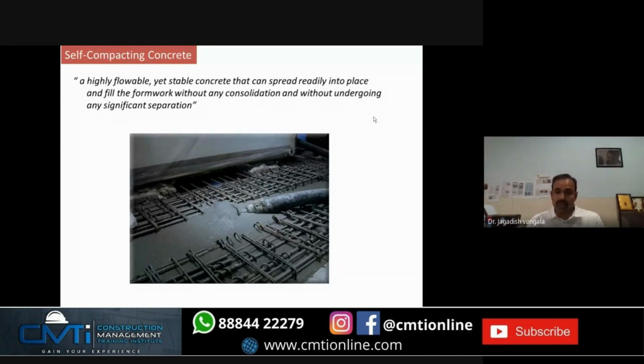You need not do any consolidation. You don't do any vibration. And at the same time, it will not undergo any kind of separation. That means while flowing, the concrete will not get separated out. What does that mean? Suppose it is flowing, in a bigger slab you have the beam reinforcement in between, so it has to pass through the beam reinforcement. If your mix is not good, all the aggregates will get stopped at this reinforcement and only mortar will go to the other side. What I mean to say is, a good SCC is a flowable, stable concrete that can readily be placed, fills the formwork without any consolidation and without undergoing any significant separation.